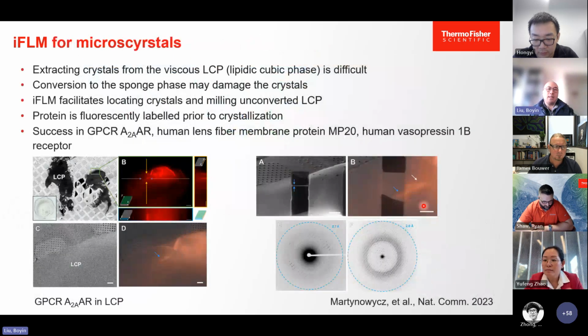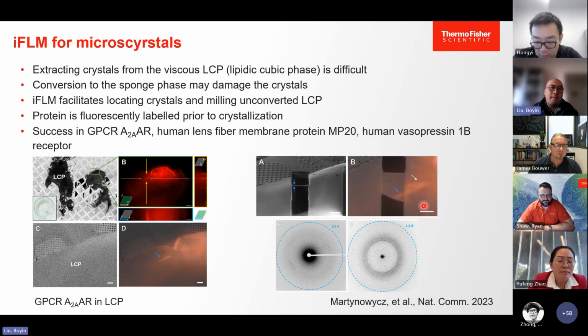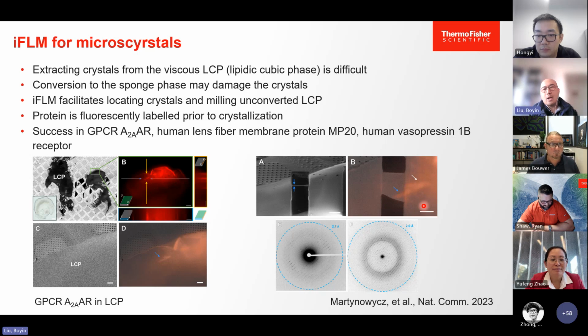And the community actually found an application for MicroED with iFLM as well recently. The paper was just published last year, and there are also a few manuscripts available which were just published this year. This is very useful in crystallizing in LCP, for example, GPCRs. But LCP is very viscous and thick, and extracting crystals from LCP is very difficult. Converting the LCP to the sponge phase could make it more fluid, but it might damage the crystals. So in this case, iFLM helps locate the crystals and mill unconverted LCP.